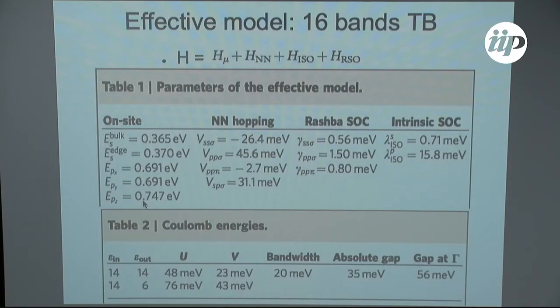So the 16 bands model that we get is precisely like the Kane and Mele model, with one very important difference. The intrinsic spin orbit coupling, when you have to hop to next nearest neighbors to stay within the same sublattice. Here, because I have on-site s, px, py, pz orbitals, I can connect within the same site. I don't need to hop to the next nearest neighbor. Okay, I can hop between different orbitals on the same site. And that's what makes my intrinsic spin orbit coupling in the p orbitals 16 meV. It's enormous. Okay, so by attributing orbital degrees of freedom to my graphene model, I got something much richer.